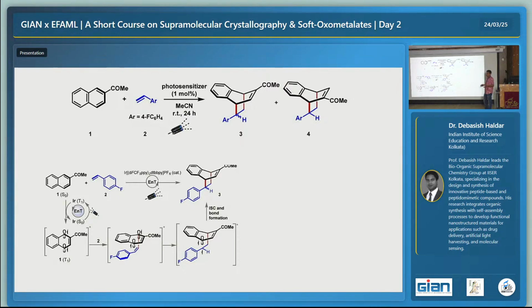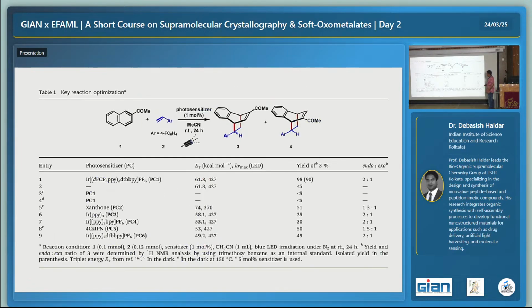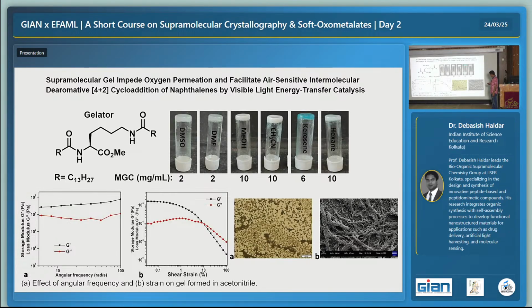Now, if you avoid oxygen. So actually for most of the reactions, oxygen is the culprit. So that attacks the transition state and demolishes the transition state, and that's why the reaction does not happen. And so what Biplav used, they used a very inert atmosphere to do this reaction. And they have done all these optimization studies, and they have reported this. And then I thought, can we do this reaction without any inert atmosphere, in a confinement inside the gel?